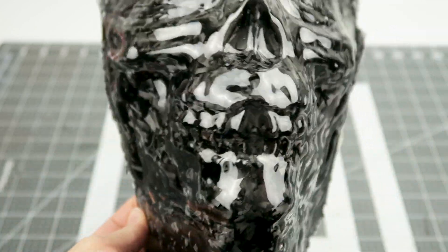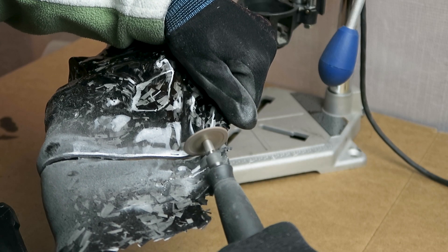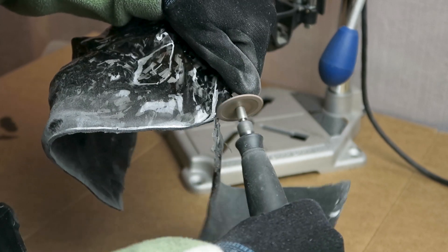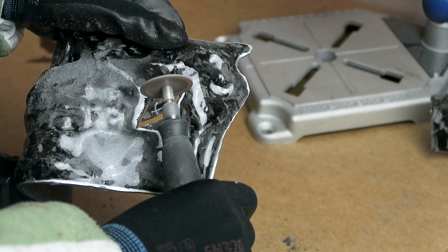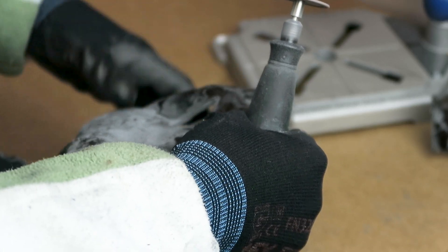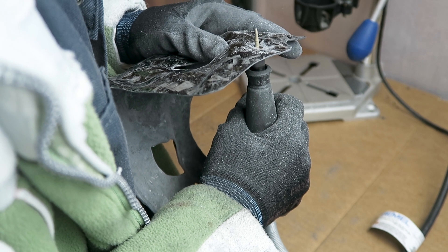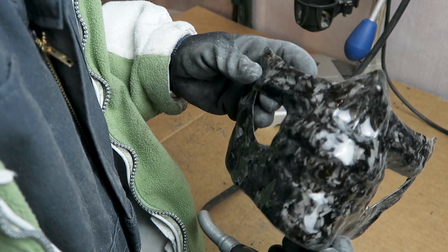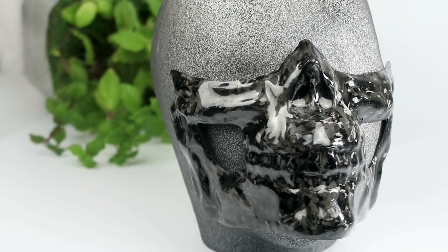This was after just one coat and the finish is good enough. It's not perfect. A small bubble trapped on the side that can be cut off, and then the area in the nose where the deepest imperfection was did sink in slightly as it was curing, and there are also a few minor air bubbles trapped in various areas that aren't particularly noticeable. If you were to spend more time, do multiple layers, do some sanding, certainly you could improve that finish, but for a quick fix where you just need to do as few steps as possible and get it to an acceptable level, this is a great way to go.